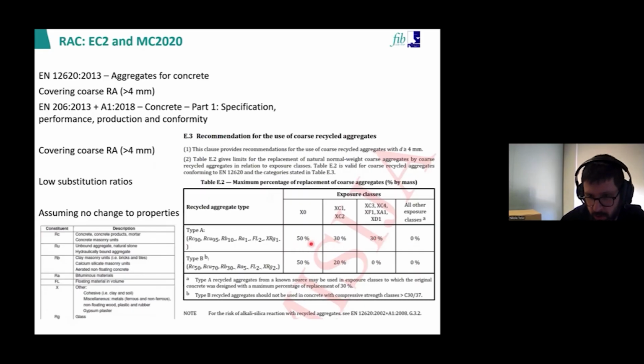But these limits are low, as you see here, and they depend on the exposure class. They are low because EN 206 does not contemplate the effect of recycled aggregate on properties. So the limit is there to ensure basically that within those limits, we don't see a loss in properties, and so you are kind of safe to use them. But now, through all the research that was done in the world, we can make models to take into account this change of properties and thereby allow higher replacement percentage.